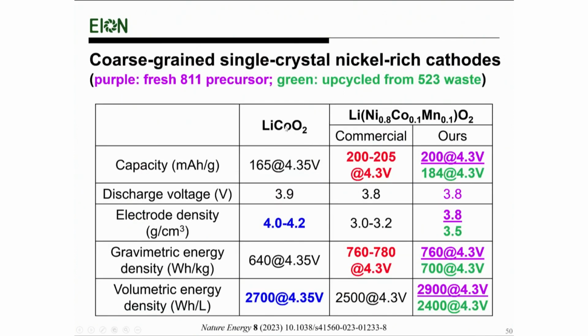And we have also developed at MIT new technologies to make single crystal NCM cathodes, which was recently published, where we can either use fresh precursors, so nickel 80%, cobalt 10%, manganese 10%, or we can use upcycled from nickel, cobalt, manganese 523. So the state-of-the-art single crystal result is in the purple.